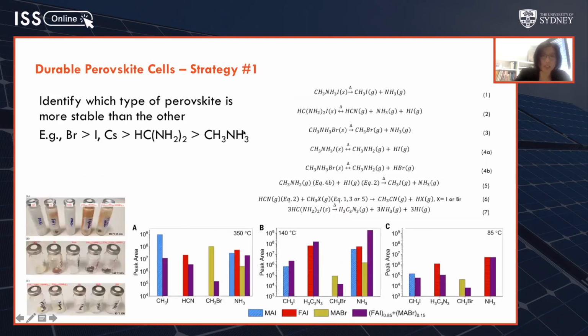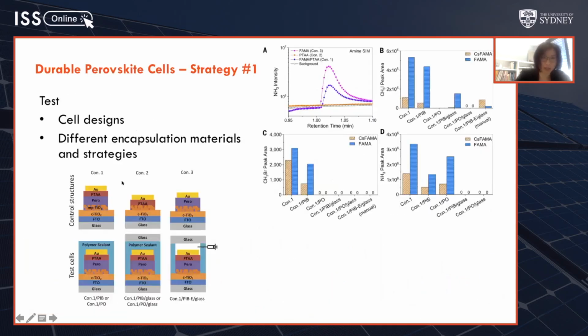So going back to strategy 1, we use GCMS to identify which component of the perovskite, and therefore which type of perovskite, is more stable than the other. For example, we found bromide perovskite is more stable than iodide. And also the cesium, the inorganic perovskite, is more stable than the formamidinium perovskite, which itself is more stable than methylammonium perovskite. And we torture them at different temperatures and see what happens. And we therefore deduce the decomposition chemical reactions.